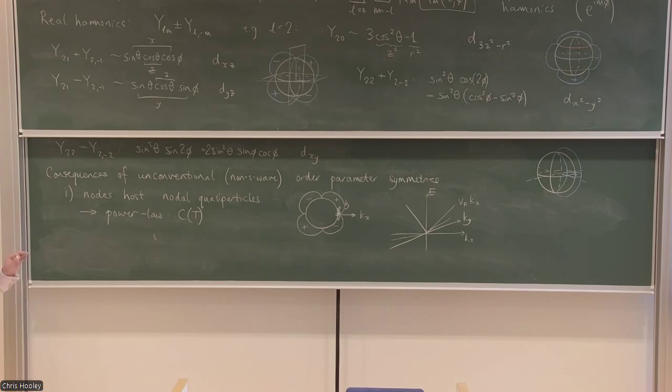So what we are doing here is saying, imagine that we had this, what would we see? It does not follow that if we see one of these consequences, we know that we have a d-wave order parameter. And lots of these features in experiment can be caused by other stuff. Whereas total destruction of the superconductivity by non-magnetic scattering, there's no way around it. That really identifies an unconventional order parameter. Yeah, and we will talk about sensitivity to disorder, and there's a nice calculation in the Markey paper that I mentioned earlier of how that works.